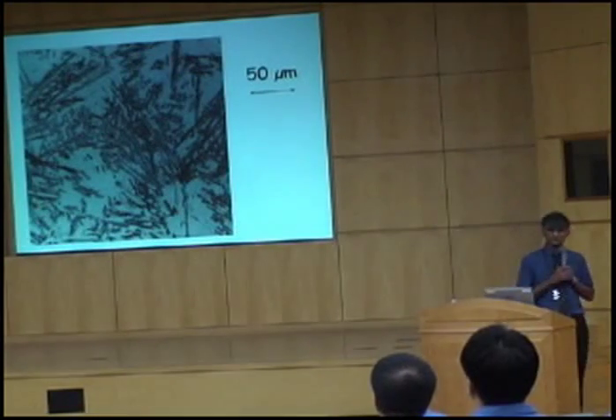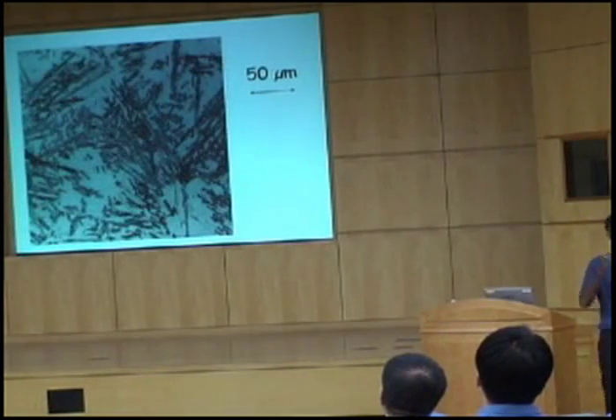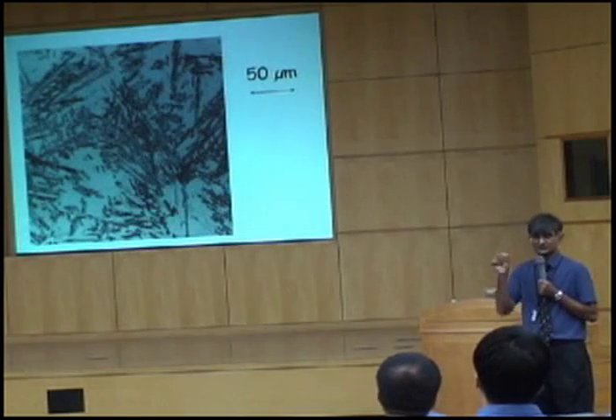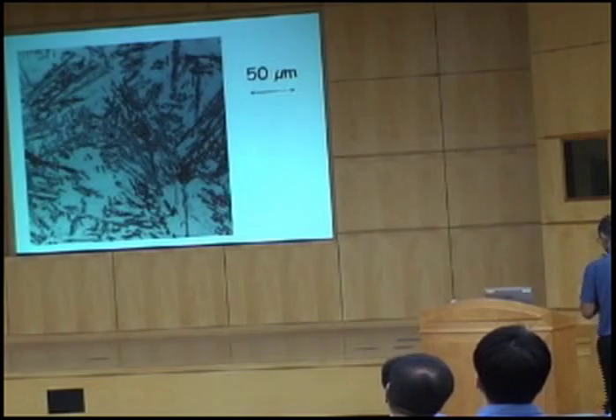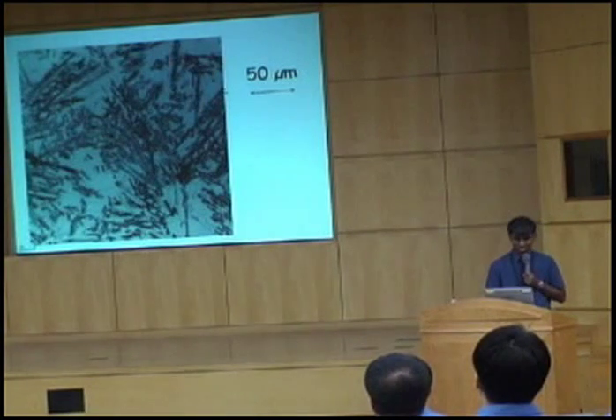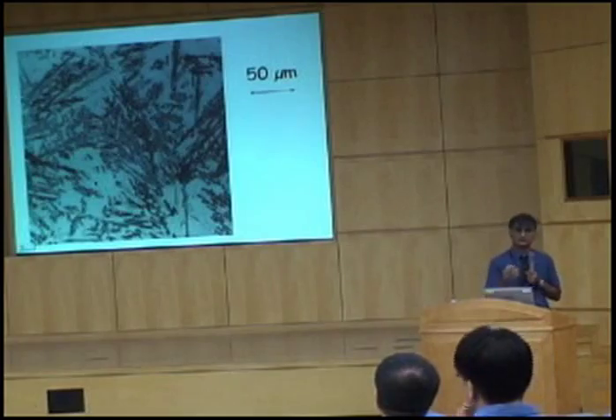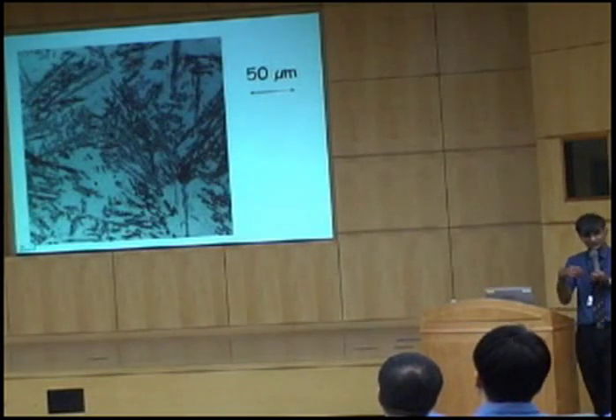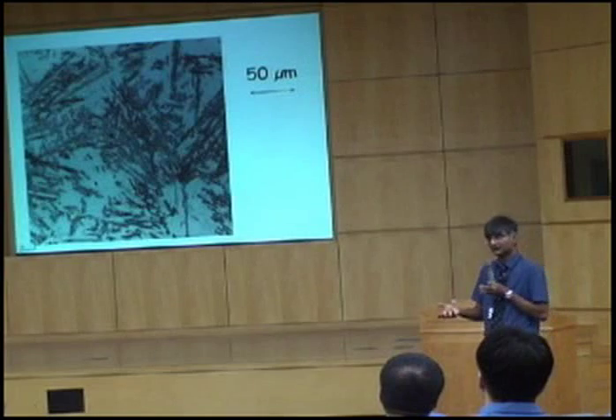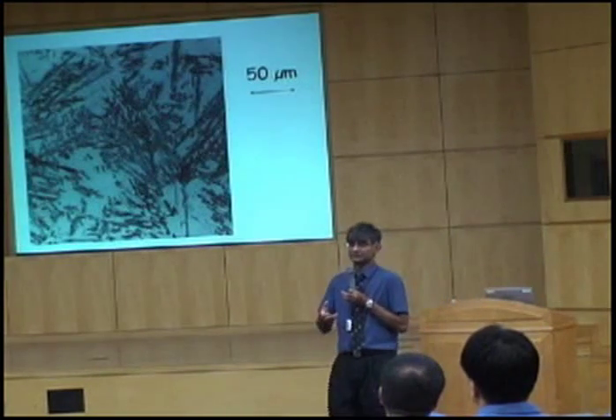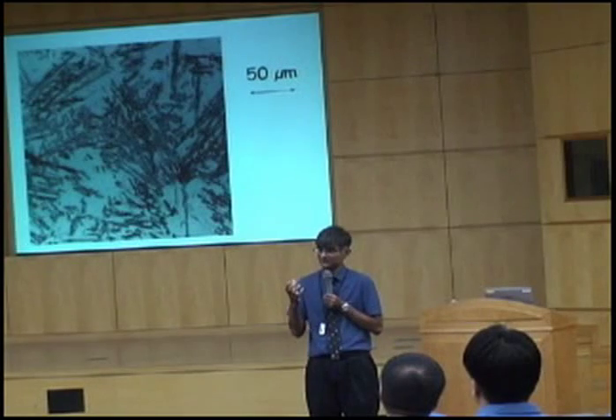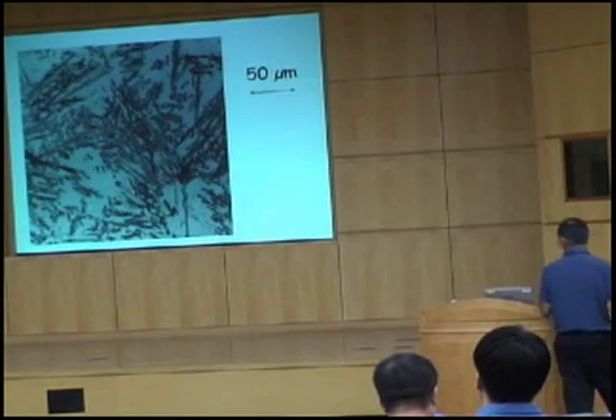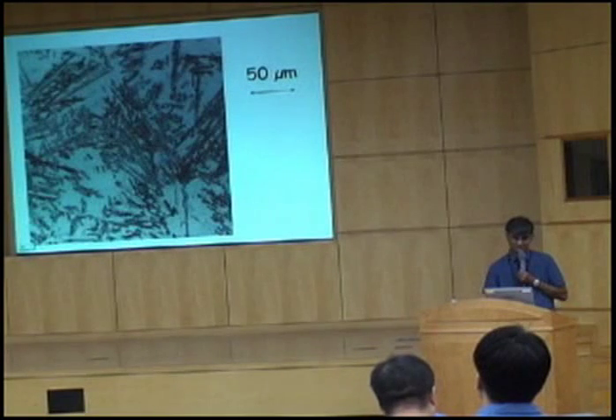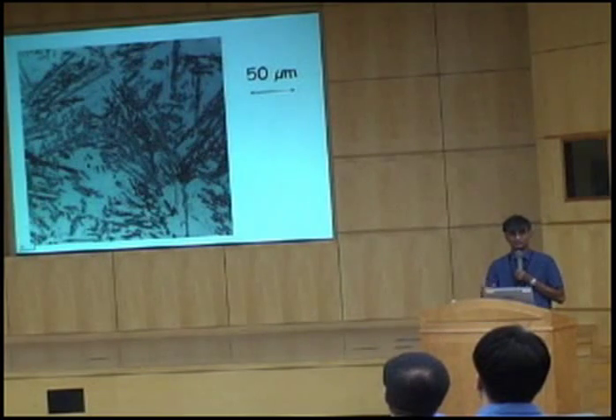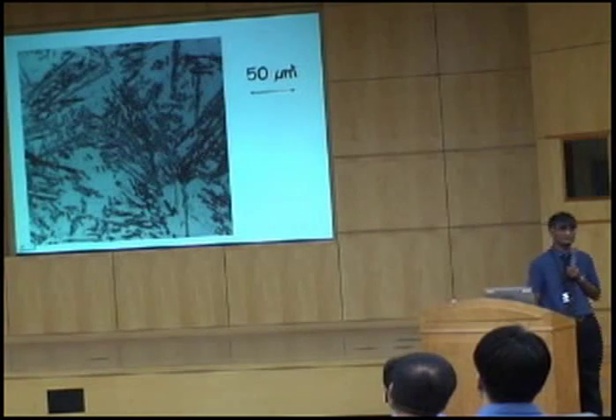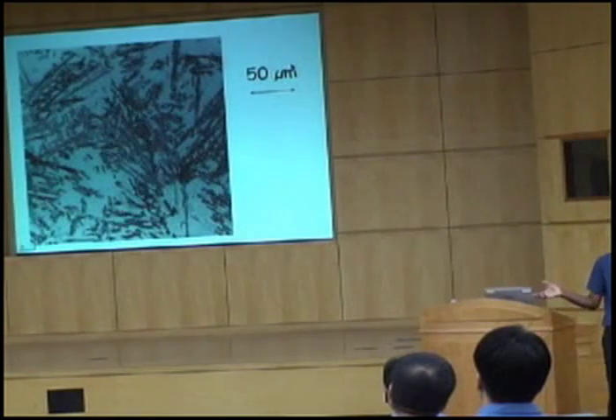Well, if you look at the optical microstructure, then in addition to those very fine films of austenite between the plates, we have these large regions here of austenite which are rich in carbon. And as soon as you apply a stress, they transform into high carbon martensite, untempered high carbon martensite, which is very brittle. So you can imagine that these regions of austenite are like hard inclusions in your microstructure, which are something like 50 micrometers in size. So your toughness is very bad.